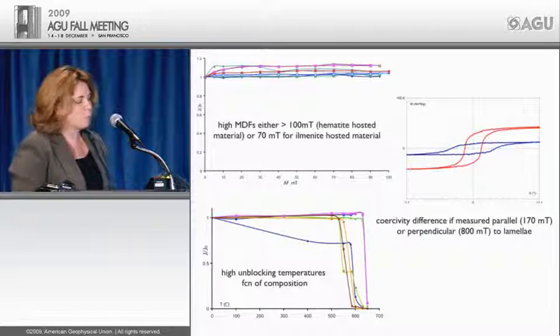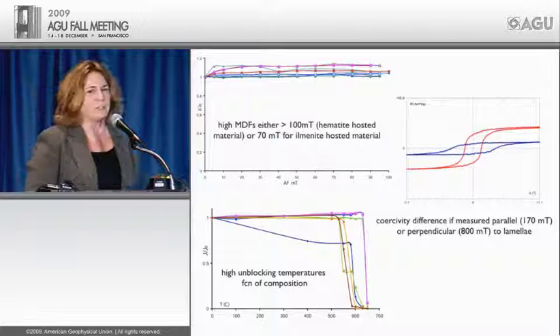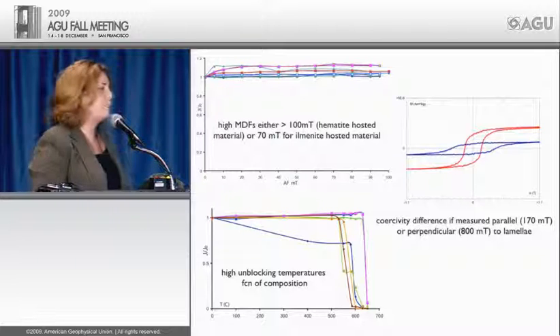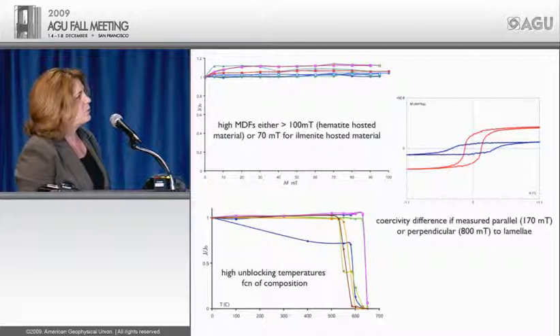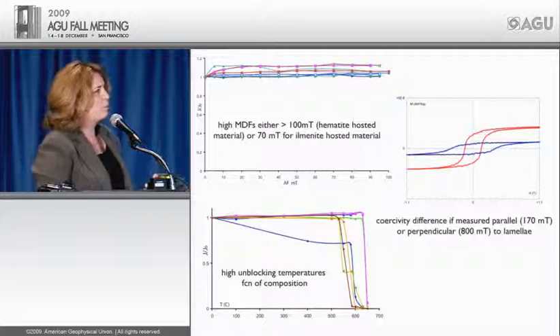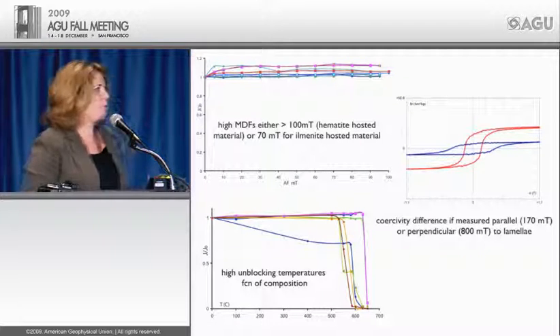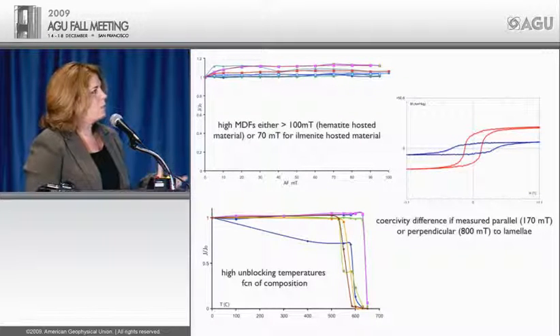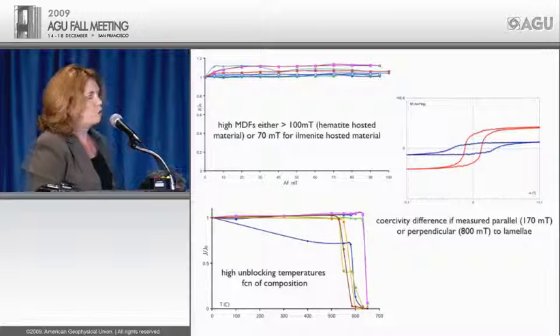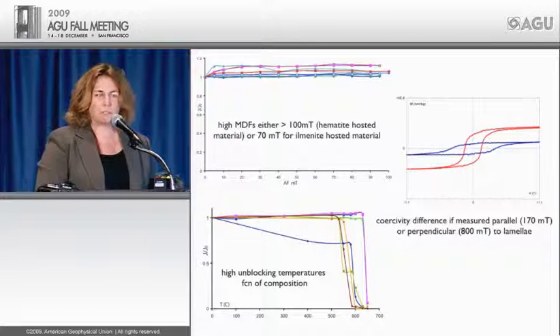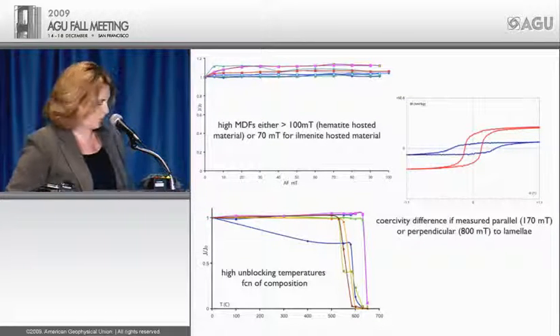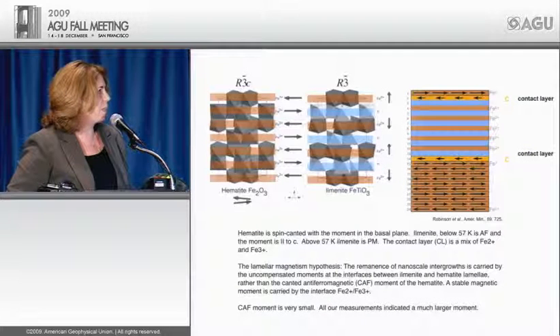The other thing is when we're doing hysteresis loops on this material, there's a large dependence whether you're parallel or perpendicular to the lamellae. And you can see a normal hysteresis loop there with maybe a coercivity about 170. If you happen to be running it perpendicular to the lamellae, that's just a minor loop, and it's at least a coercivity of 800 millitesla. So these are very hard, stable magnets.